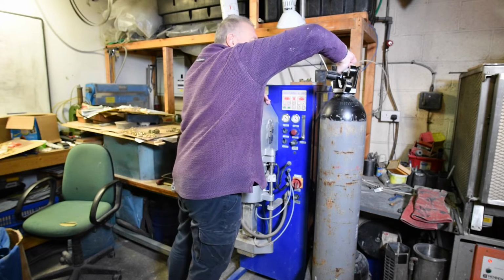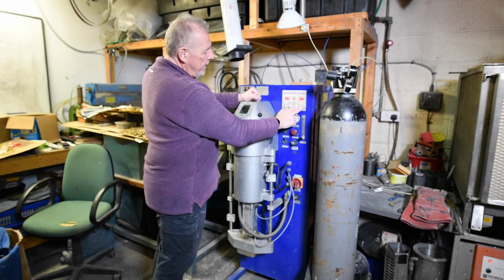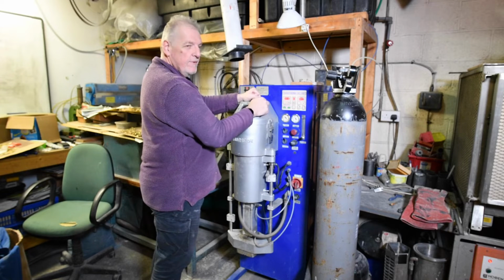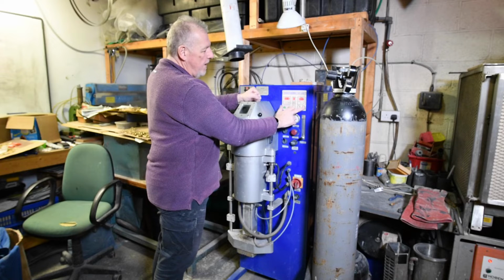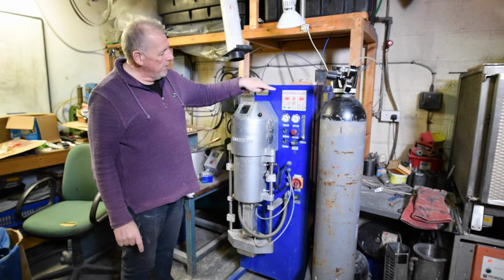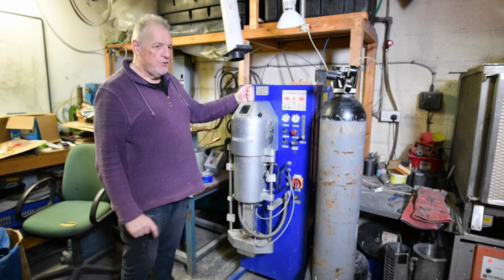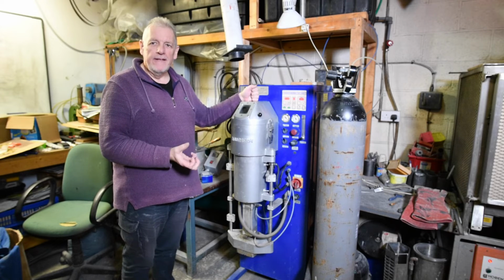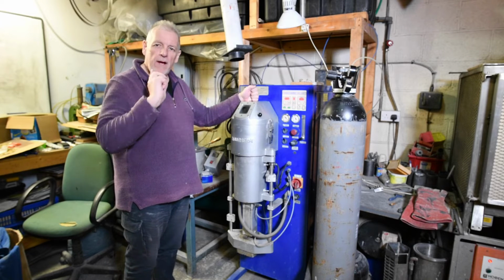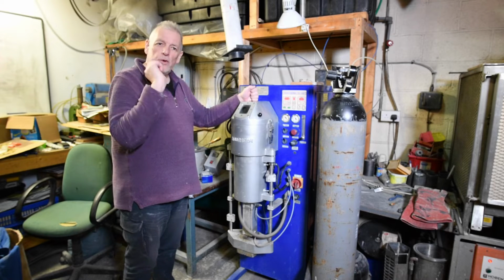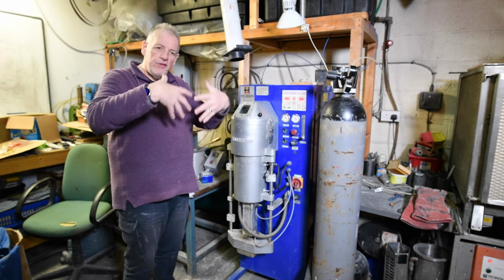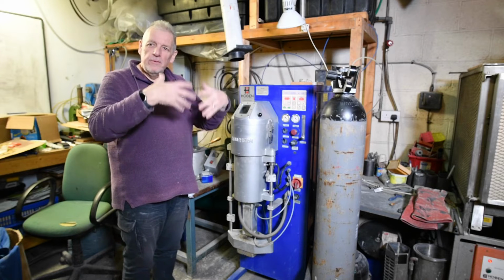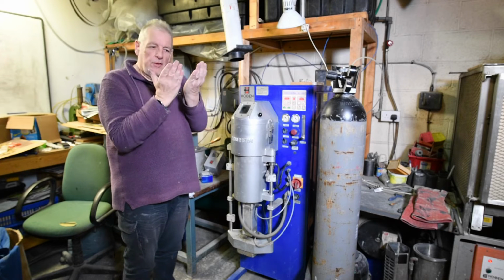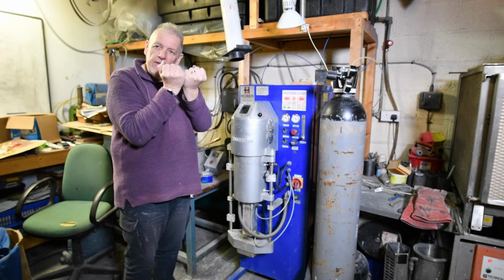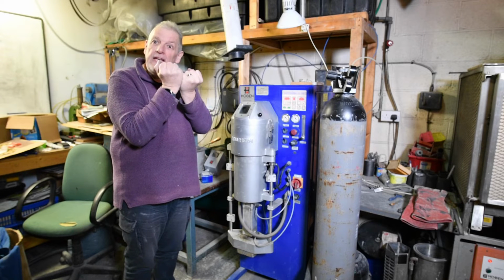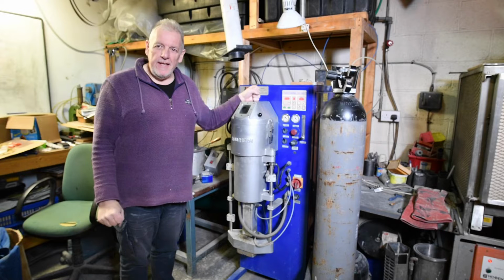So we'll turn the nitrogen on, and then we turn the machine on, and if you watch this dial here, you'll watch the temperature rise in the crucible. So there's now heat going to the crucible. It's called induction heating. It's a copper coil around the crucible through which water is going to keep the coil cool, and there's an alternating magnetic field, which is called induction, which makes the molecules of the graphite crucible rub together to create heat, and that will give us the heat that we require.